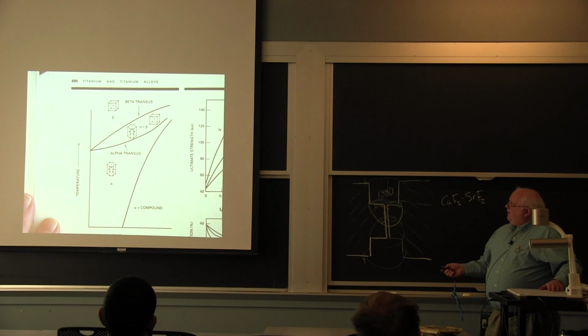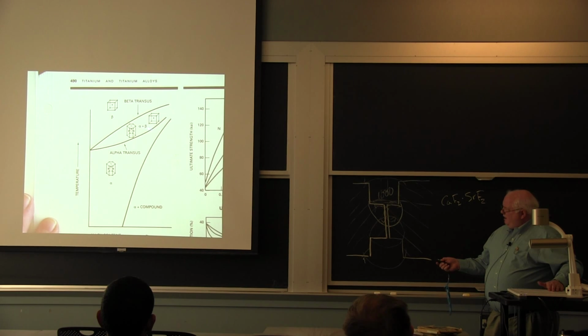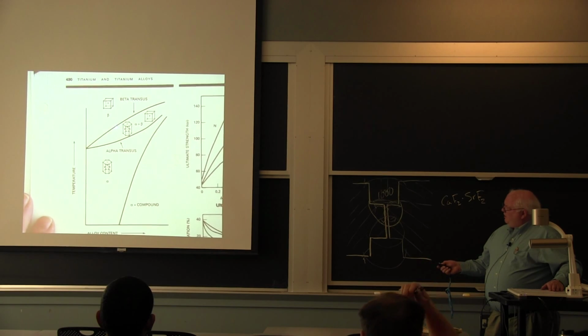And if you have an alpha stabilizer like aluminum in your titanium, at higher temperatures with more aluminum, you stabilize the alpha phase. In fact, titanium 6 aluminum 4 vanadium is an alpha beta alloy that has both crystal structures. I'll show you more about that later.